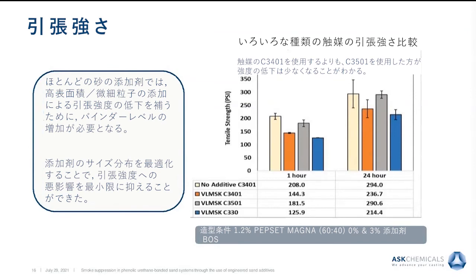Of course, we can monitor other time points, but just to illustrate here, you can see no additive, and this is of course made with, again, 1.2% Magna, 60/40. We have 0% for no additive and 3% for the rest of the samples with sand additive. And you can see that we're not surprised about this. There is a reduction in tensile strength from the use of the sand additive at 3%. But the way we recover our tensile strength is by adjusting the catalyst to a different catalyst with maybe higher active ingredients. So that we have now 3501 here, and then we are already kind of back to where we want to be. Remember, the error on these tensile experiments is probably 20%.